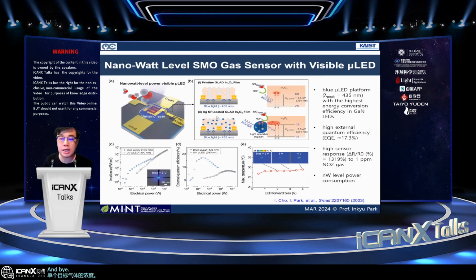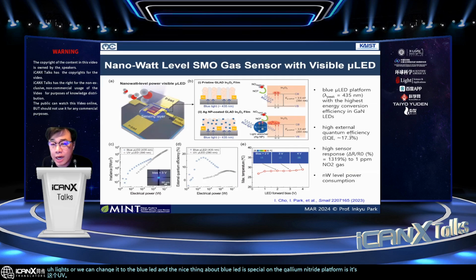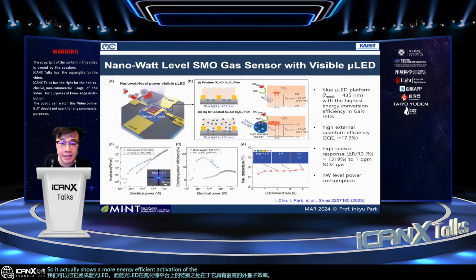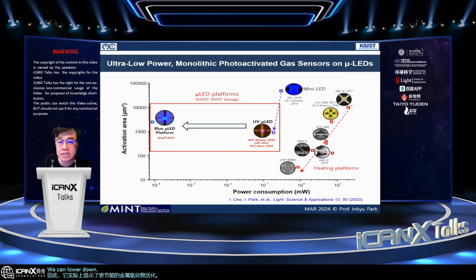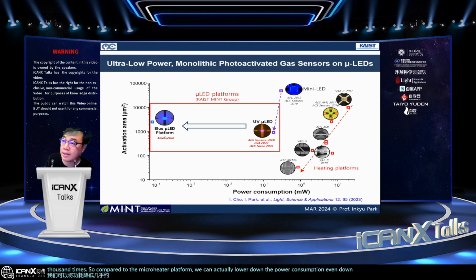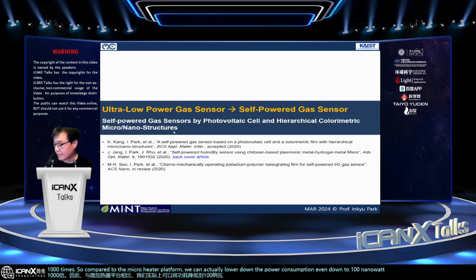And by changing this UV light source, we can change it to a blue LED. The nice thing about blue LED, especially on the gallium nitride platform, is it has high external quantum efficiency. So it shows a more energy efficient activation of the metal oxide. So we can lower the power consumption by about 1,000 times. Compared to the micro heater platform, we can lower the power consumption even down to the 100 nanowatt level, which we are quite excited about.